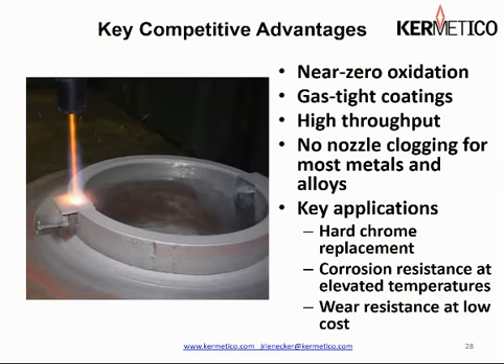And we can provide extraordinarily high wear resistance at an extremely low cost, mostly because of the quality of our coating. We can use a much thinner coating than in traditional thermal spray. So in traditional thermal spray, where you might need 10 or 20 thousandths of a coating, we can get away with 5 to 8. So we're using even less material, further increasing the efficiency of the process.